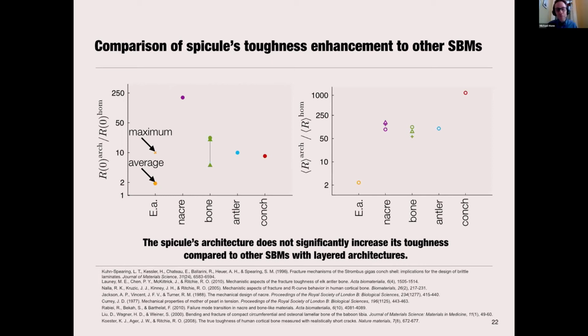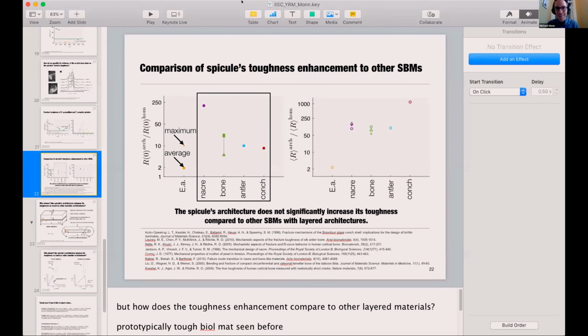So what we really found is that compared to these other materials with layered architectures, like nacre, bone, antler, and conch shell, the enhancement in fracture toughness, both in initiation toughness and in this average R sort of metric for toughness, is very, very small. It doesn't really compare at the same scale. You don't see the huge enhancements that you saw in these other materials. An enhancement of a factor of 2 to 10 is still very impressive in an engineering sense. But it leaves this mystery as to why this particular material doesn't perform like these other materials. The secret to that lies in the geometry of the layers, the curvature of the layers. So I'll end there, and if people want to hear more during the break, I will stick around.